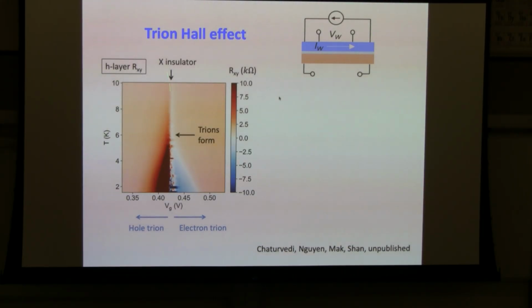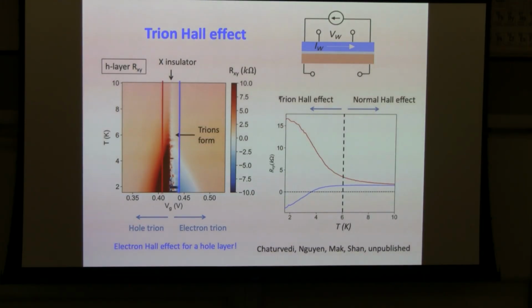This is the position for the excitonic insulator. On the left side is holes. You're putting more holes into the system. On the right-hand side, you're putting more electrons into the system. The trions form below about 6 Kelvin-ish, something like this. And let me show you 2 line cuts here along these 2 dashed lines. At very high temperature, the Hall effect of the hole layer just behaves like a normal hole layer, that you just get the density and the sign correct of a hole layer in this high temperature regime.